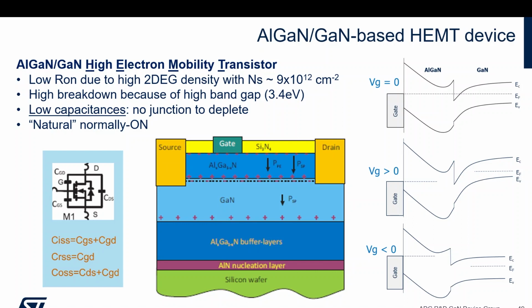Then, of course, due to the properties of the GaN, you end up having this situation here in which at the interface between the GaN and the AlGaN, or anyhow the barrier, you have a 2D electron gas due to the polarization effect and the difference in the band gap. The 2D gas has an important property, which is that it has a certain density, and especially the mobility is very high. Because while in silicon, typically the electrons are associated to phosphorus or arsenic ions, so you have scattering due to the positive or negative charged dopant ion. Here, these are free electrons, so there is no associated scattering. So this mobility can be as high as 10,000 centimeters squared per volt per second.